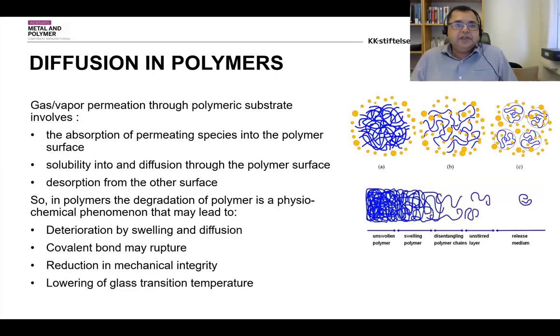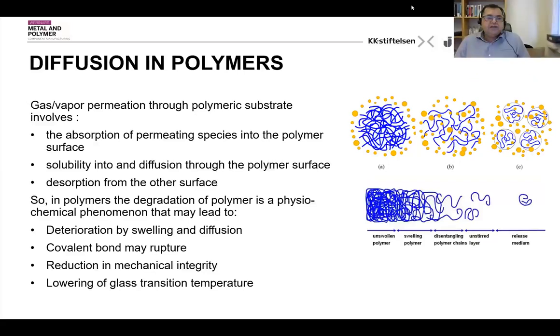So the barrier properties of a polymer are actually related to the diffusion process, which is related to the migration of small molecules such as oxygen, water, carbon dioxide, nitrogen, and water vapors into the polymer barrier films. This process actually involves three main steps: the absorption of permeating species into the polymer surface, their solubility into and diffusion through the polymer, and desorption from the other side.